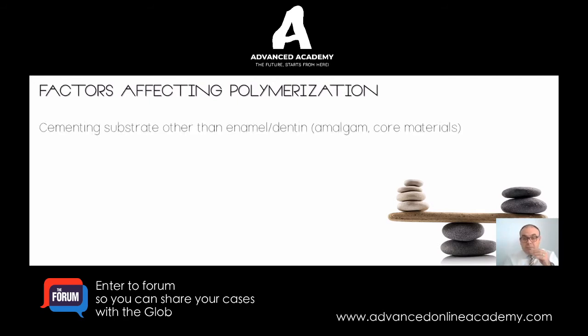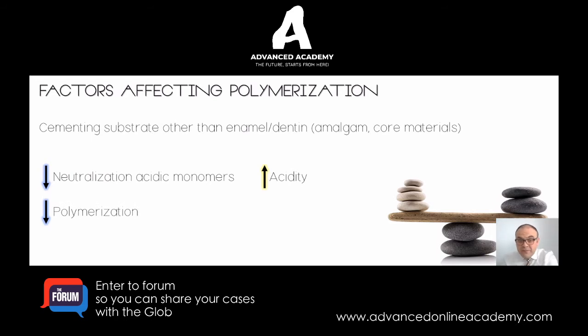So what if you're not cementing onto natural dentin, right? If you have enamel or an amalgam or any core material, what's going to happen is that the neutralization of these acidic monomers is really going to go down. You're going to have increased acidity of the environment there. The polymerization is not going to happen as well either, and so therefore you're going to have water absorption.